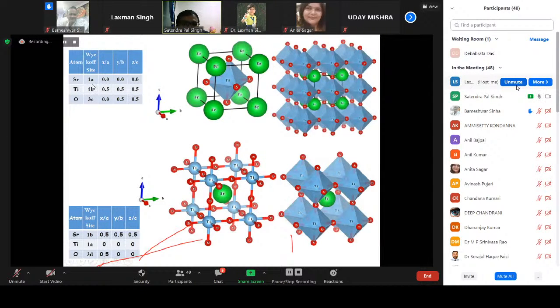So see, the strontium at the 1A site, titanium at the 1B site, oxygen at the 3C site, this is the perovskite structure. Titanium lies at the body-centered position, the strontium lies at the corners, and oxygen lies at the face-centered positions. So you will have this kind of perovskite structure.